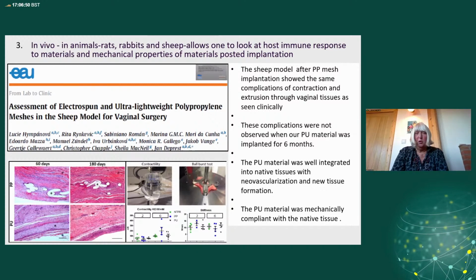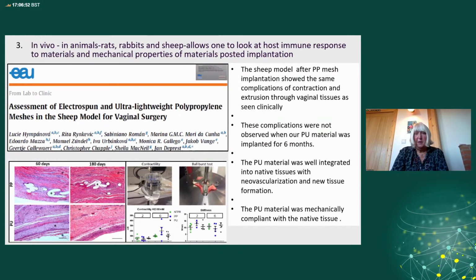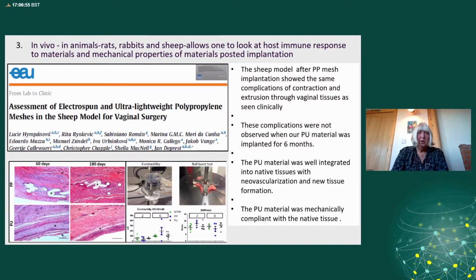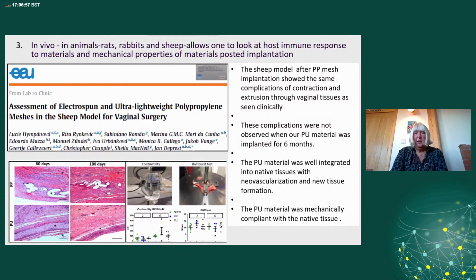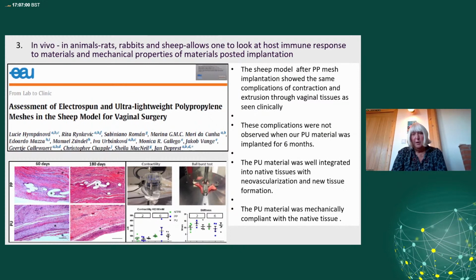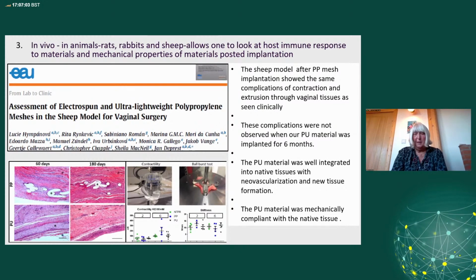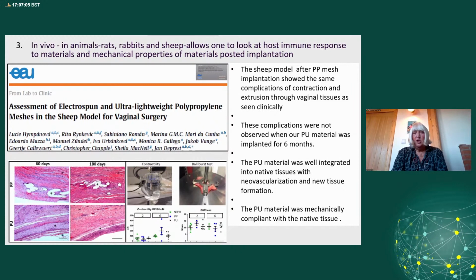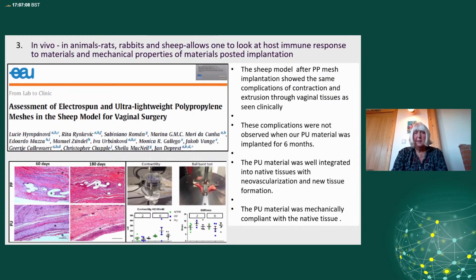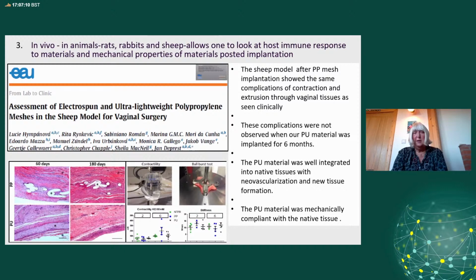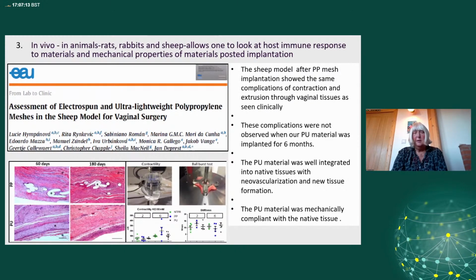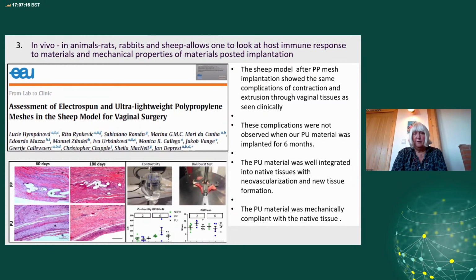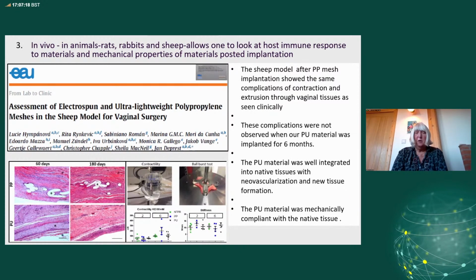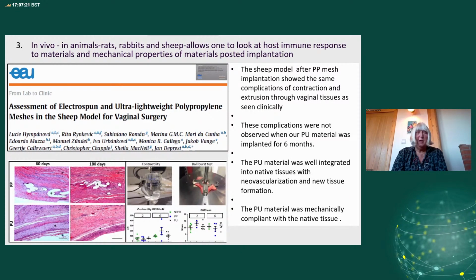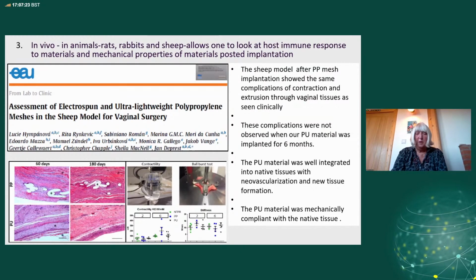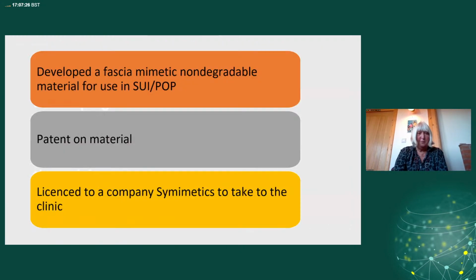Now, the beauty of the sheep model is it's the first model, to the best of my knowledge, that allows one to show that the same material implanted in the abdomen does quite well, but implanted in the vagina does really badly. Polypropylene mesh implanted in the abdomen contracts less than 10%. Implanted in the vagina contracts more than 50%. And in some sheep actually eroded through the vagina of the sheep. So the value of this animal model is that it shows up the complications that we find happen in some women when they receive polypropylene mesh.